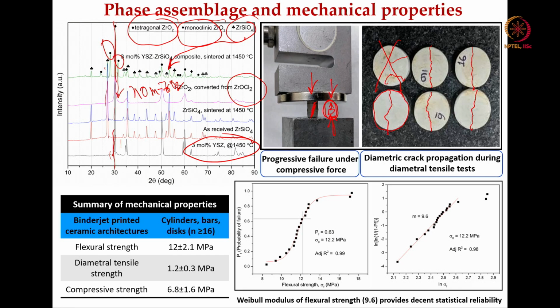So, what is the tensile strength you are measuring? It is very low, it is 1 MPa, because it is a highly porous structure. Compression strength is around 7 megapascal, and flexural strength is around 12 megapascal for n greater than 16. That is, more than 16 samples were used for these measurements.